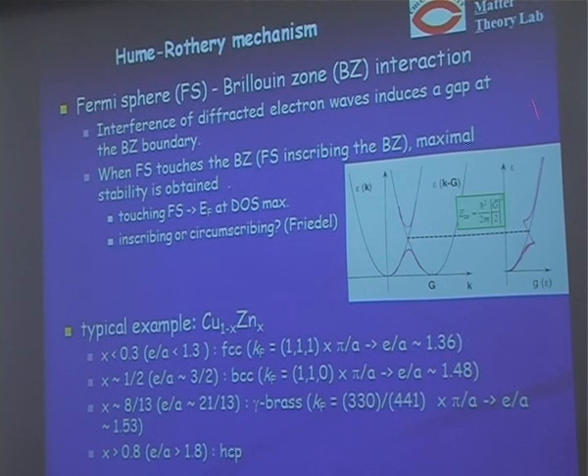And in the electronic density of states, we have the peak and the dip. And actually, the free electron energy at the zone boundary is just between the peak and dip in the density of states. And if the states below the gap are occupied by electrons, we expect a gain of the boundary energy. And the maximal gain would be obtained if all the states are completely occupied by electrons. So in that case, the Fermi level comes here, and the Fermi wave vector corresponds to just the zone boundary, which is the bisecting plane of the reciprocal lattice vector.